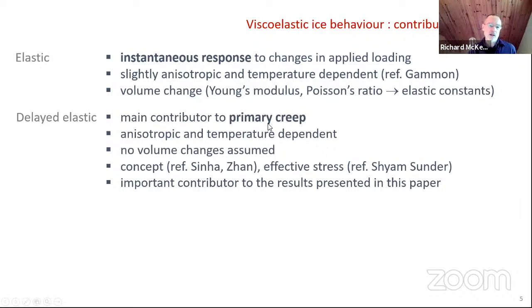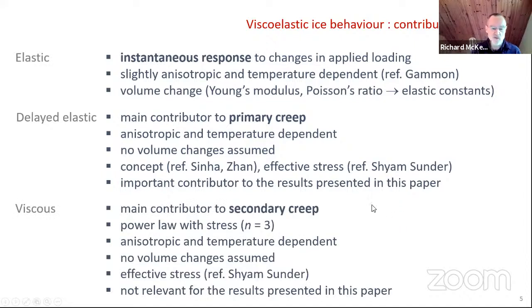The delayed elastic part is the main contributor to primary creep, and that's an important contributor to the results in this paper. The assumption is a standard temperature dependency for creep. The behavior is anisotropic, and we rely on, as documented in the paper, Sinha's work and his student's, and also the effective stress measure that Shyam Sunder used a few years ago. We also include a viscous component, which is a power law for secondary creep, but for the short times we look at in this paper, it's not relevant.